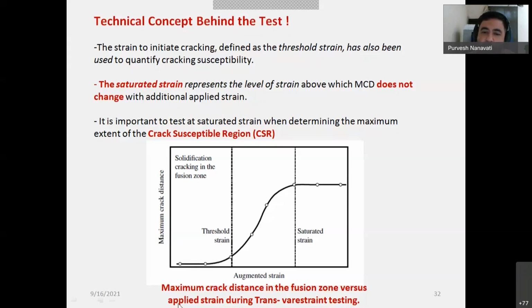So you look at this graph, which is developed as a result: maximum crack distance, this is MCD, versus augmented strain. Now, when you plot a graph using these two, you would see that for solidification cracking in the fusion zone there will be some amount of strain already. That is known as threshold strain. It means you require some strain to develop the crack, right? There is only initial cracking. That is known as threshold strain.